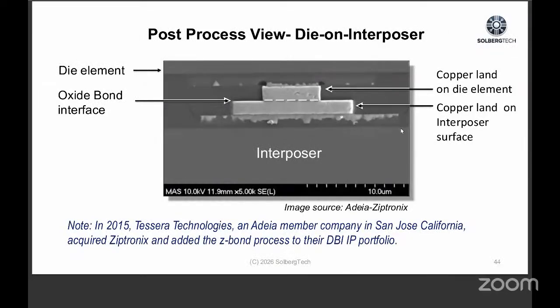This is a cross section of a joint. Now, this is showing an interposer on the bottom and the die on the top, and you notice I have a slightly different diameter pad or terminal, and that just helps with alignment. There are some companies that are actually going size on size, but the alignment of these products in high volume is very, very delicate. So I always like to have one of the pads larger than the other, so you're sure to get metal to metal interface. So this is showing the die element, the oxide bond surface, and the copper land.